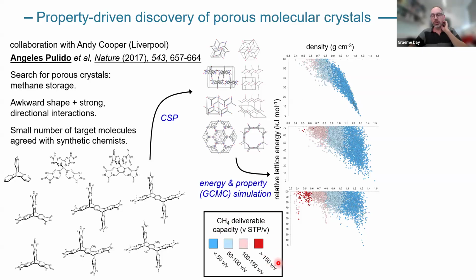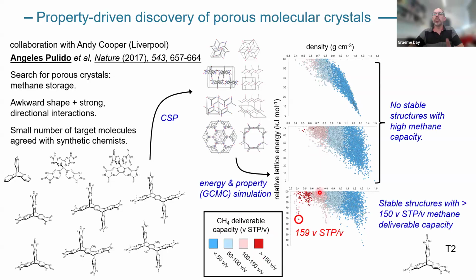And what I want you to look for are red points on these graphs. What those correspond to is the target range of methane deliverable capacity for those materials. We want to be above about 150 standard temperature pressure volumes of methane per volume of material. What this lets you do is look at a landscape quickly and decide, is there anything on that landscape that could give us the property I'm after?